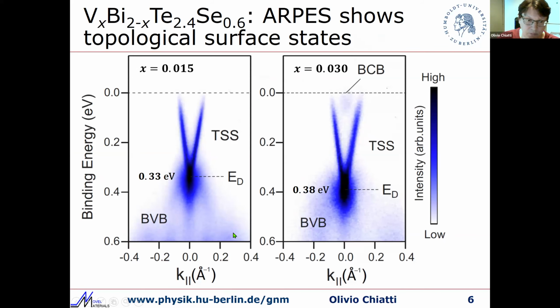We see the bulk valence band, and we see that the chemical potential seems to be in the bulk band gap. Increasing the vanadium concentration seems to shift the chemical potential to higher energies. That means the binding energy of the Dirac point becomes larger, and we start seeing the effect of bulk conduction bands, which means in both samples, the chemical potential seems to be fairly close to the bulk conduction bands, which should yield some effects in the transport measurements.